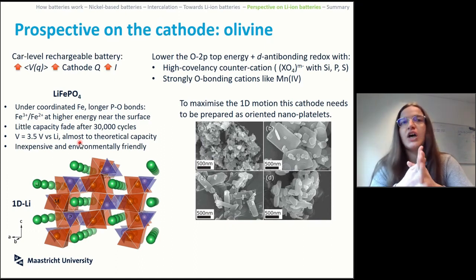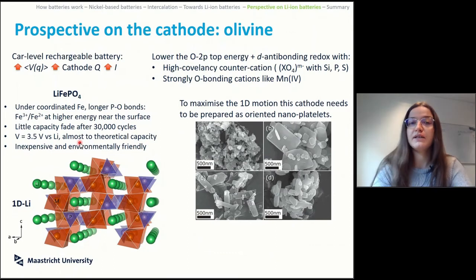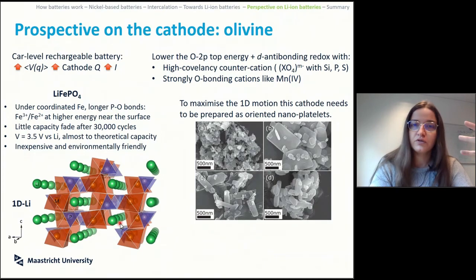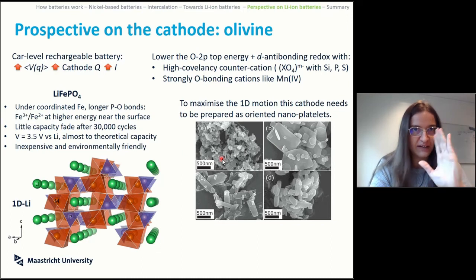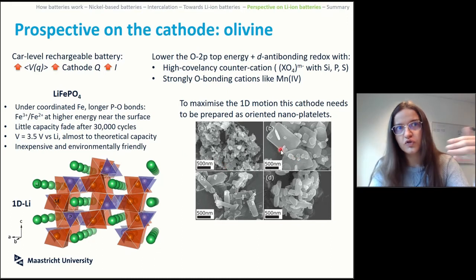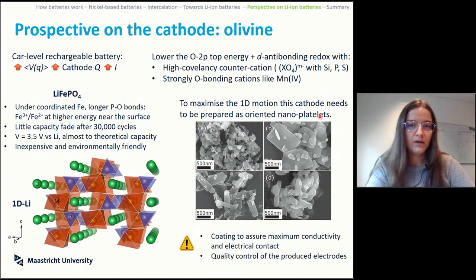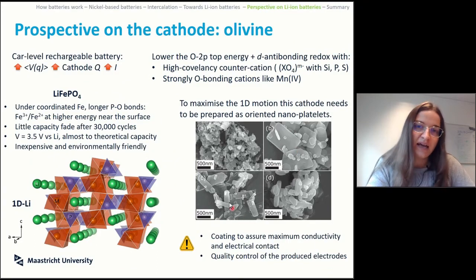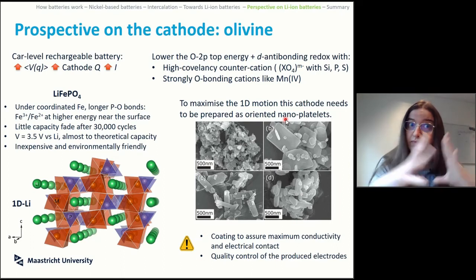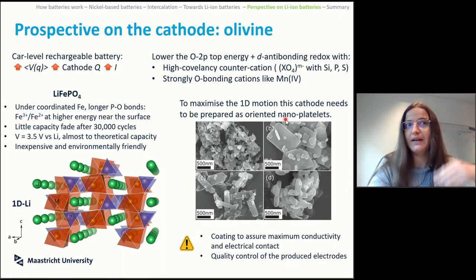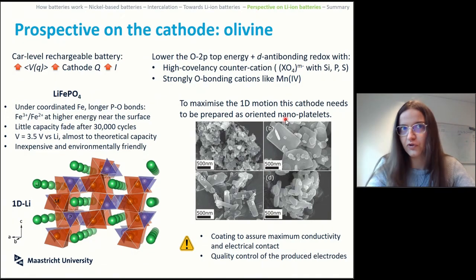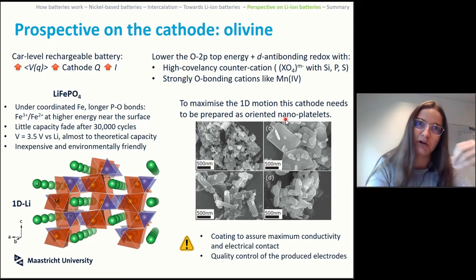But since we are going in channels, in only one specific direction, it means that your cathode needs to be prepared in a way that optimizes this crystallographic orientation. So you tend to do this with oriented nanoplatelets, but this of course adds steps to the actual synthesis method. The coating would ensure the maximum conductivity, but to do the coating, you need to add an additional step. And the quality control of this thing, since you wanted such precise microstructural control, so you built your structure, how is it actually arranged, will add steps over steps of quality control of the electrodes to make sure that this thing that you just made is exactly equal to the previous one.